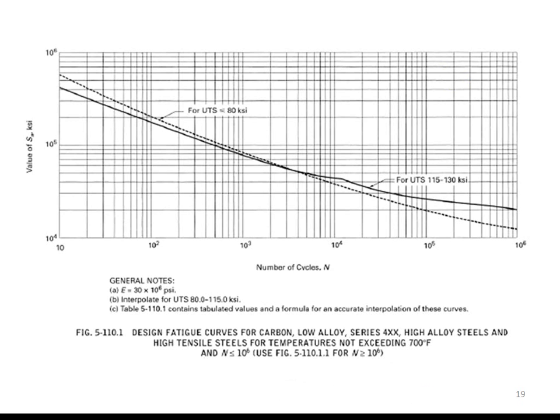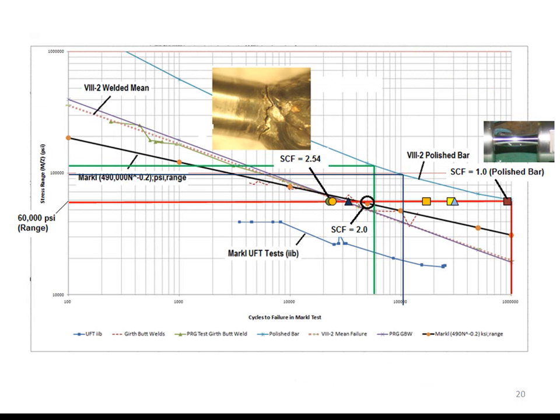the ASME axially loaded polished bar fatigue curves. We can put the PRG rotating bar test failures on the ASME curve along with some other test curves to see the comparisons. The welded specimens are to the left of the Section 8 Division 2 polished bar curve, and they have stress concentration factors of from 2.54 to about 2.